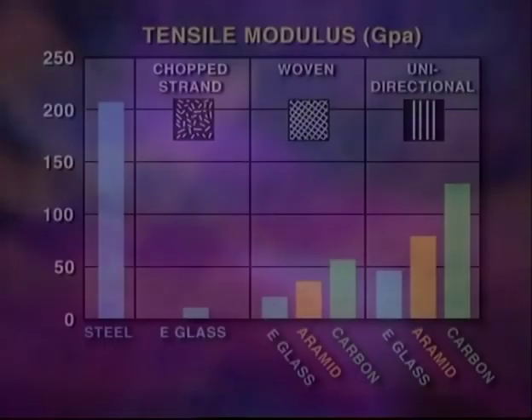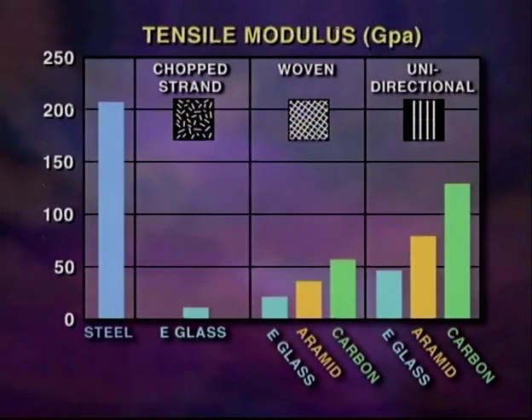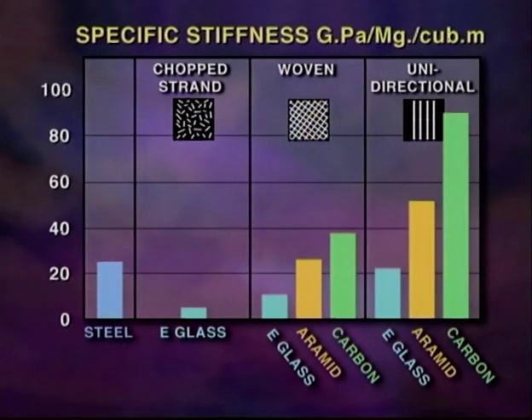The other property that is very important for structures is tensile modulus, which is a measure of stiffness, and in this, steel is well ahead of any of the composites. Faring by far the worst in this comparison is chopped strand mat with a modulus of 8 compared with steel at 207. But when relative densities are taken into account, then carbon fibre materials have outstanding specific stiffness.